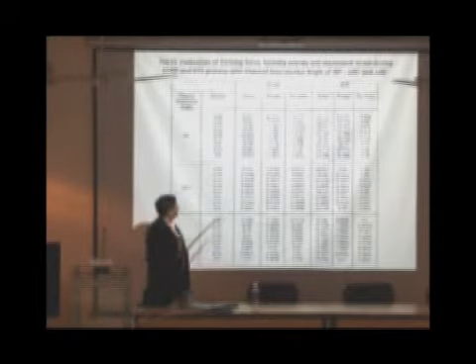The best method I will try to convince is ECAP in which there are some chances of commerciality. These are the various results of our study to help the community, what are the best process parameters for this ECAP process. We have tried for different die angles 90, 105, 120 degrees for different friction coefficients. The main criteria is to obtain equivalent plastic strain.